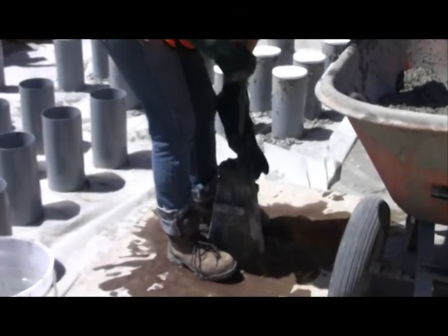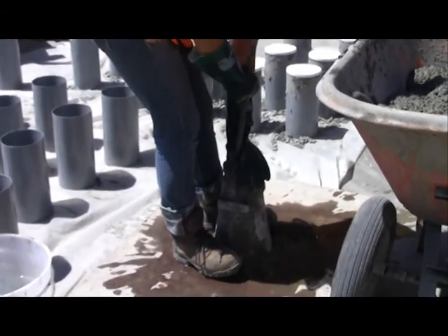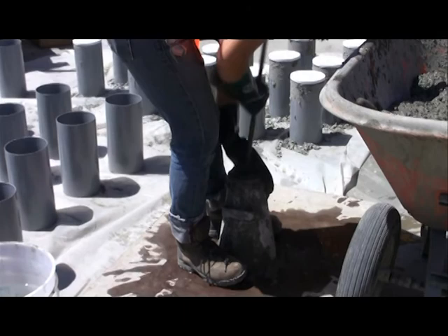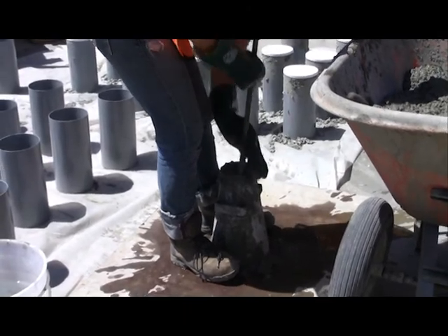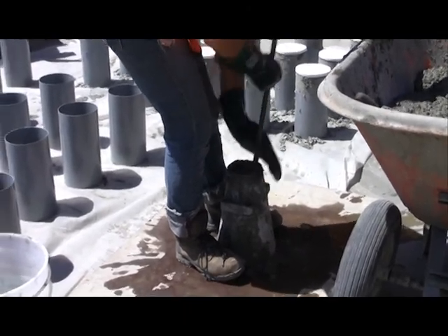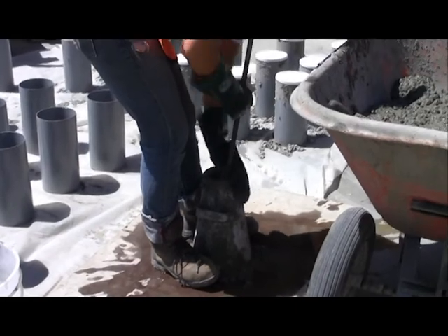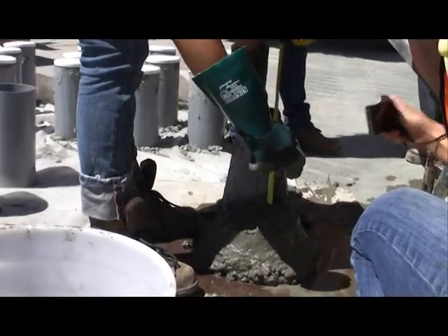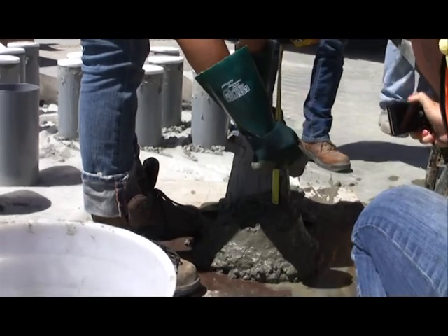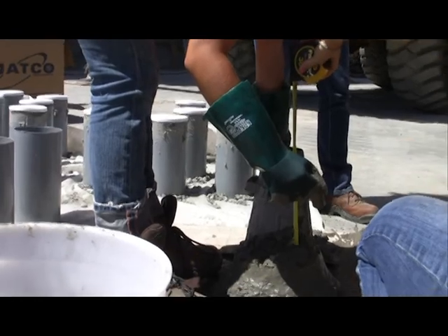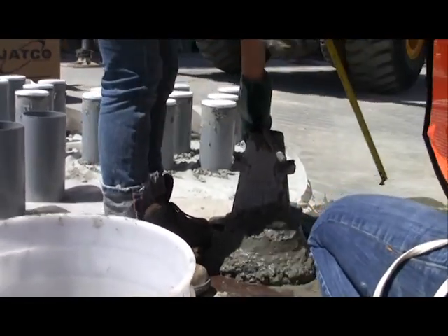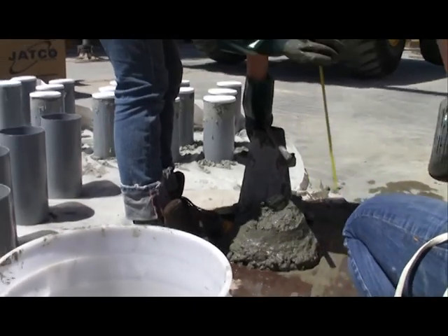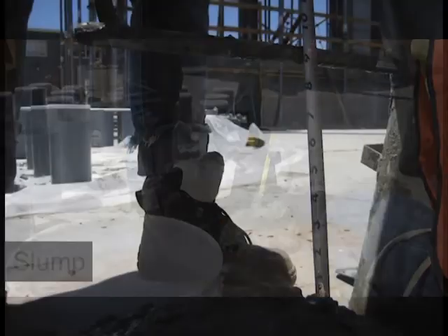In a slump test, a cone-shaped mold is filled with wet concrete. A metal rod is inserted into the top of the cone and pumped up and down 25 times. This helps eliminate air bubbles and increases the homogeneity of the concrete mix. The cone is then lifted slowly and placed adjacent to the free concrete that is allowed to slump down under its own gravitational weight. After the slump settles, the metal rod is leveled horizontally on top of the cone, and the distance from the horizontal rod to the top of the concrete is measured.